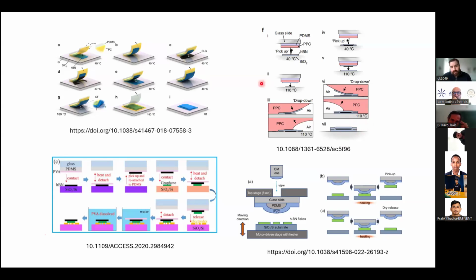Now, most of these techniques are films. So when you go down, you will come in contact at a certain point of the substrate, and then it will create a line, a contact front, let's say, that will progress until it reaches the heterostructure. On the way to reach the heterostructure, it will pick up everything. And you don't want that, because sometimes that makes picking up the heterostructure or the flake very hard. So what you do is this.